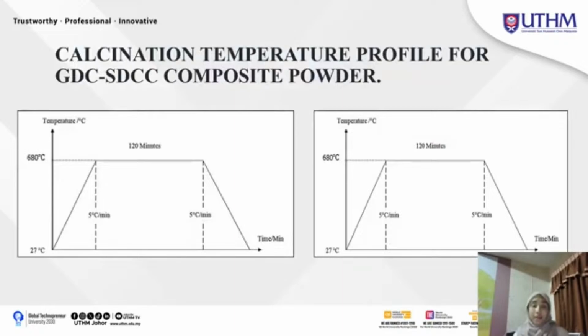So here's the graph of the calcination temperature profile for GDC SDCC composite powder. The first one shows it's exactly the same, but I will explain how this actually works for the graph. Here we can see that the duration for calcination is 2 hours, like I said before. The graph shows temperature on the y-axis and time in minutes on the x-axis. It starts from 27 degrees Celsius, and the maximum it can go to is 680 degrees Celsius.